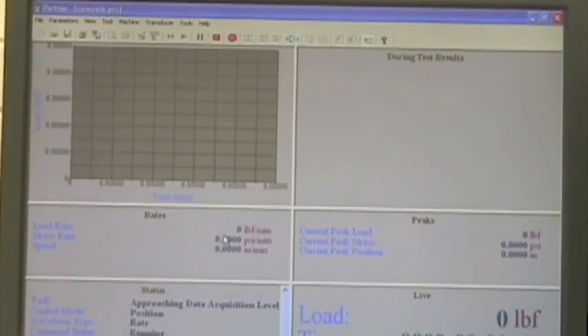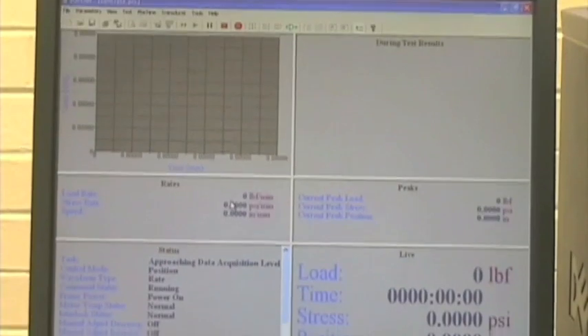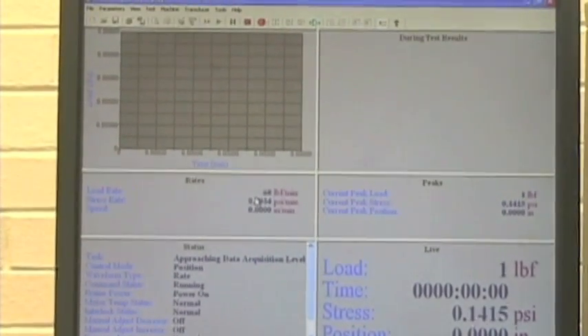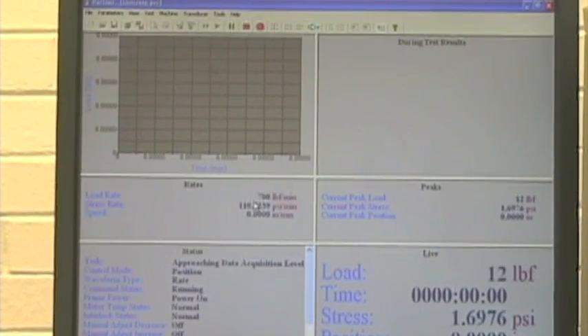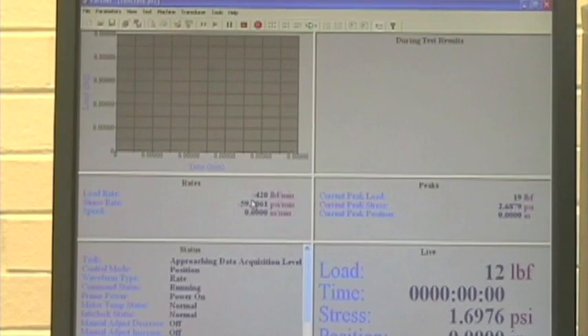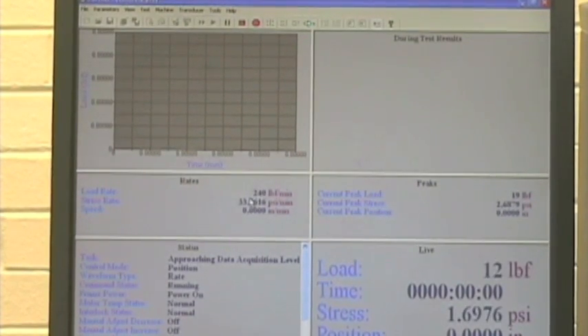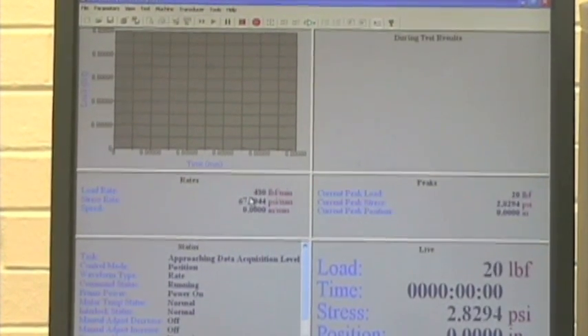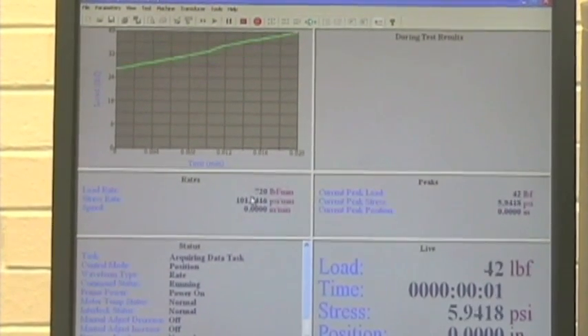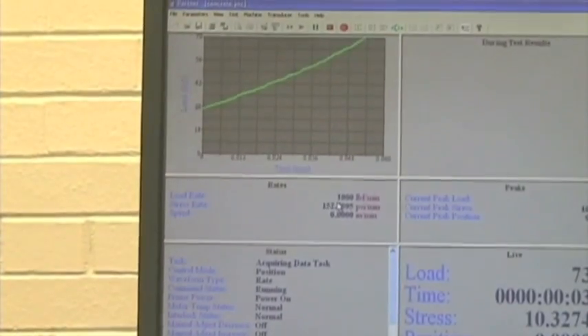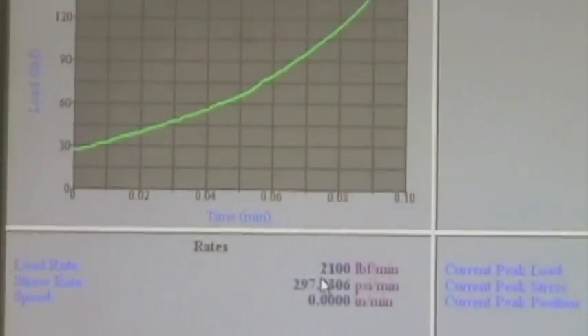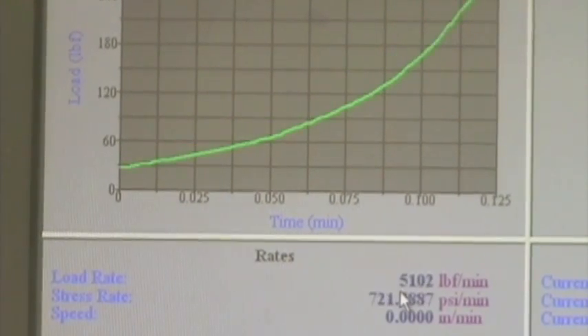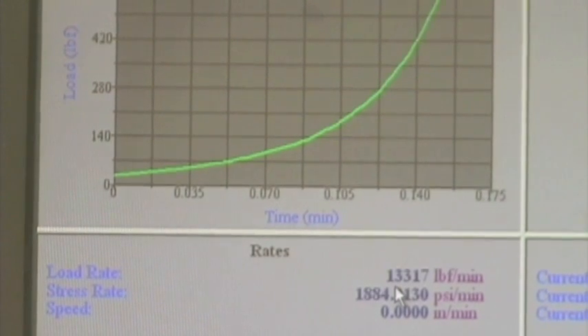Now we're going to want to put our switch into neutral. Hit pump start. And we're going to be playing with our gauge. Load rate control gauge here until it gets to about 10,000. We want to make sure that it stays between 8,400 and 21,000.